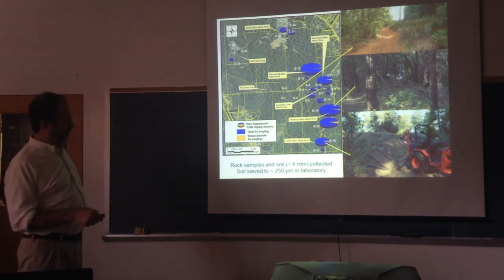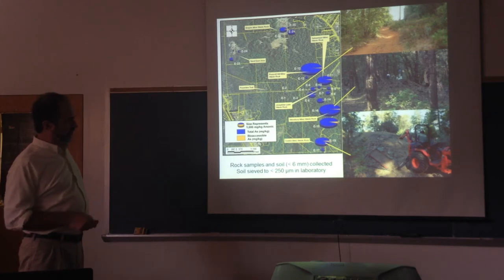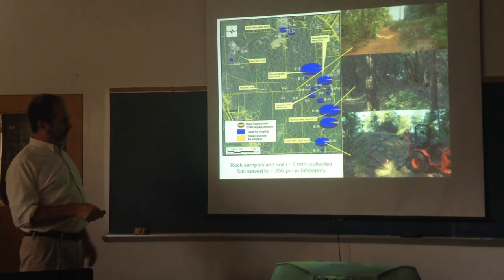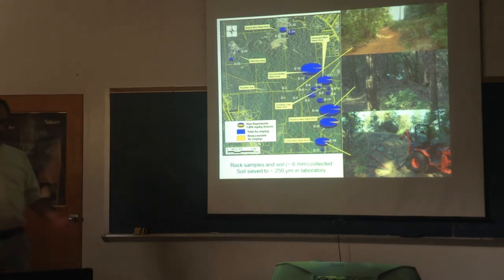And we excavated that with the help of our local contractor, and they dug with the backhoe. They actually put it through a quarter-inch screen out in the field, filled up a bunch of buckets, and sieved it down, and then they shipped several buckets of the material to Ohio State, where they put it into less than 250 micron size, and split that and sent it out to all the researchers. But they had a large stockpile of these well-characterized samples for future studies, and that's what Nick Bosco, our collaborator, says. This stuff is worth more than gold, because when you spend thousands of dollars to characterize material, you still have more of it. People want to borrow it and put it in different tests, and it's really useful to have these well-characterized materials.